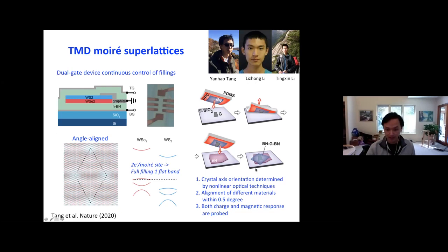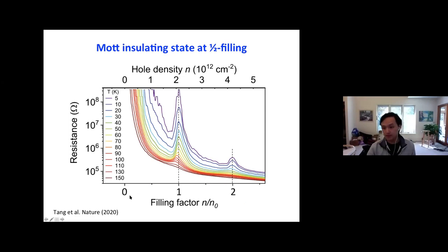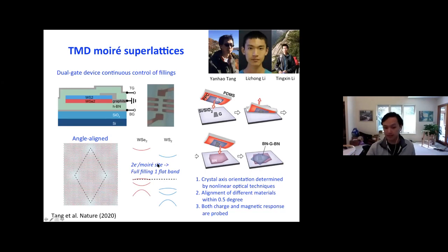And in terms of experiment, we probe both the charge and the magnetic response of this bilayer system. So here is a simple example of a 2-point resistance measurement, not 4-point, 2-point. This is resistance versus filling factor, at filling factor 0, 1, 2. You can see that as we decrease the temperature from 150 Kelvin, two resistance peaks are seen, at filling factor 1 and filling factor 2. And there is a divergence of resistance at filling factor equal to 0, and that's expected because a 0 filling factor corresponds to the Fermi energy moving out of the moiré band and into this big band gap, which is 1 to 2 eV.